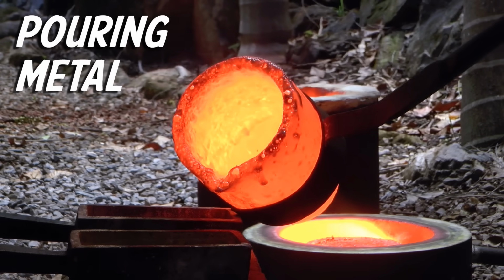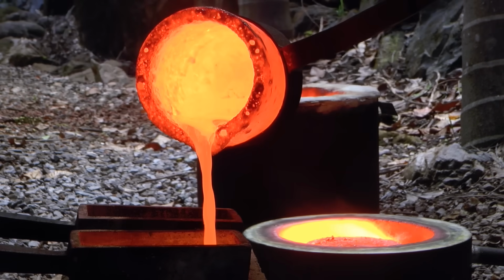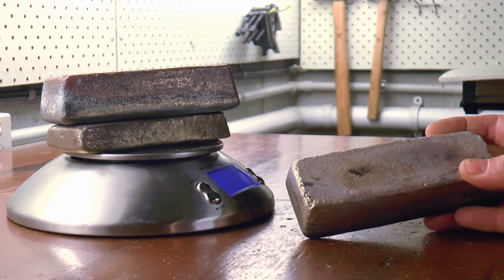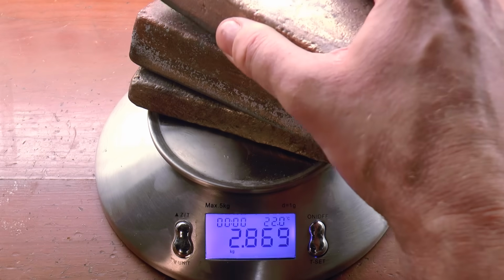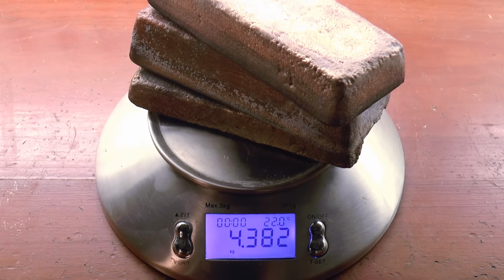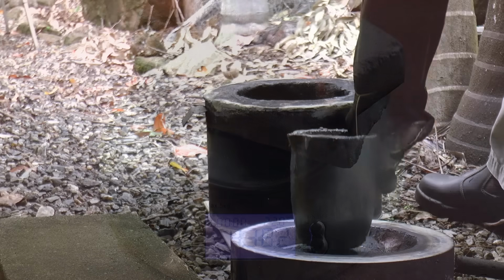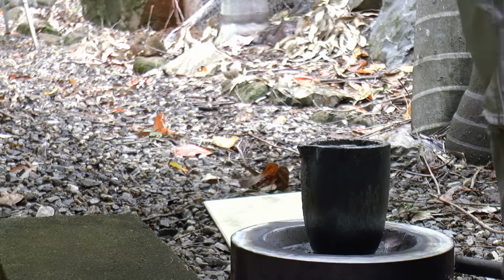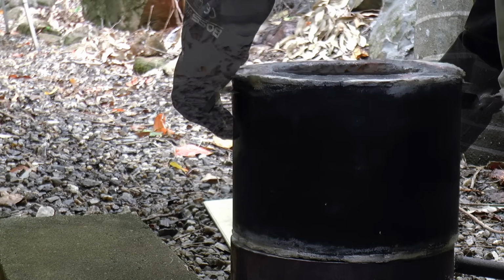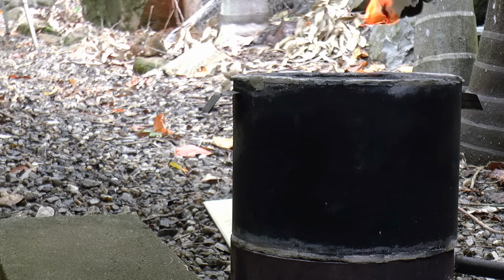Silicon bronze is an excellent metal for this sort of casting. It's probably the most user-friendly of the copper alloys in terms of its behaviour when molten. Based upon the weight of the wax pattern, I have a reasonable idea of the quantity of metal required. Once the crucible is charged, it's into the furnace that I described in episode 3 of this Tools Glorious Tools series.